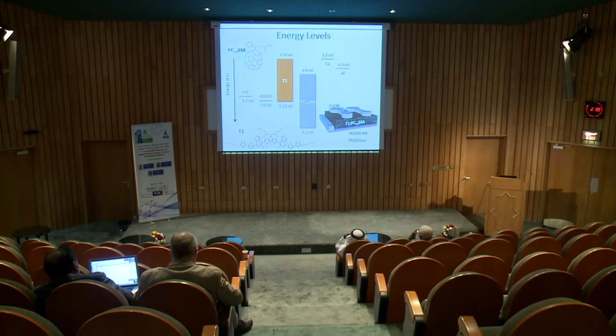And now we actually blend the film molecule into PC70BM. So PC70BM will be the electron acceptor and the T1 will be the electron donor. From the energy point of view, you can see that the T1, which is the orange, has a LUMO level that is higher than the LUMO level of PC70BM, 3.34. So there is a driving force for electrons to transfer from T1 to the PC70BM. And then to complete the device, we make the cathode with calcium and aluminum.